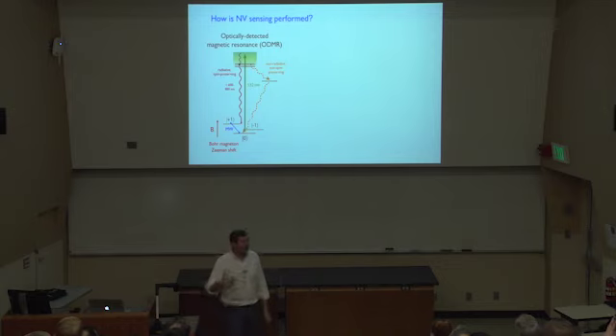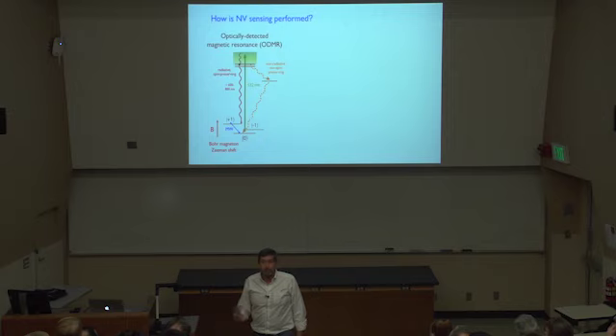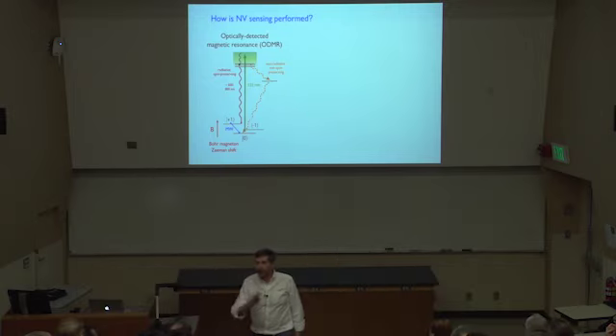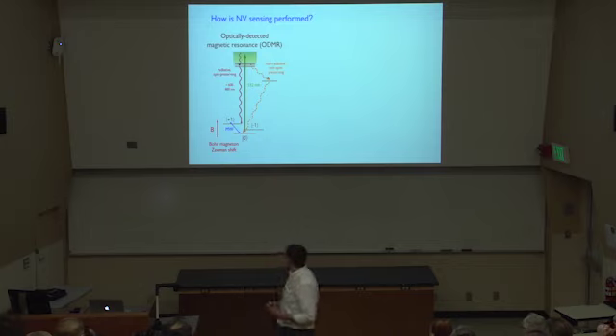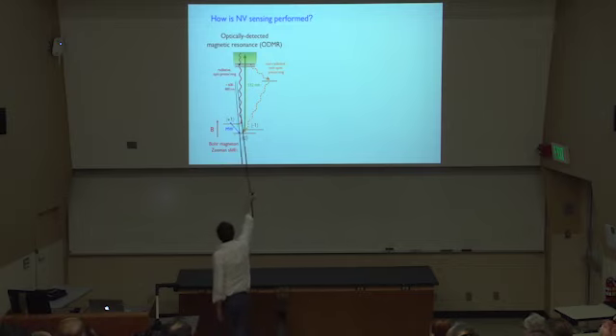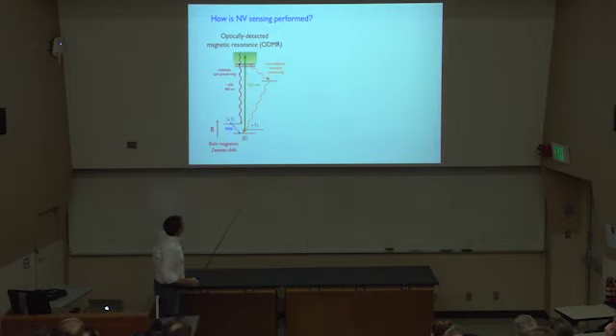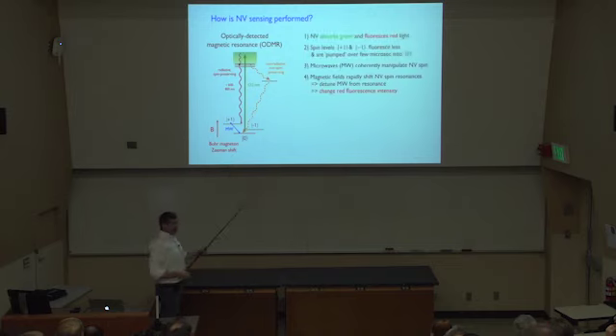But then, of course, the plus and minus 1 levels will shift with a Zeeman shift if you apply any magnetic field. And that rapid shifting of the energy levels with magnetic field is the source of the magnetic field sensitivity. So ultimately, you're going to be doing some sort of spectroscopy to determine how those energy levels shift, to determine everything. It's coupled with optical transitions to the electronically excited levels, and so you typically are going to absorb green light and radiate red into the vibronic sidebands, as shown here. So that's what you do. The NV, step 1, absorbs green and fluoresces red.